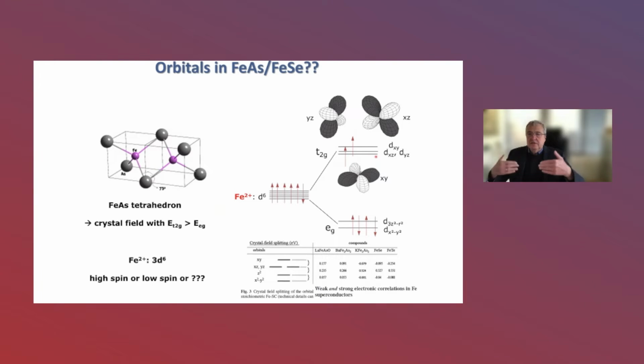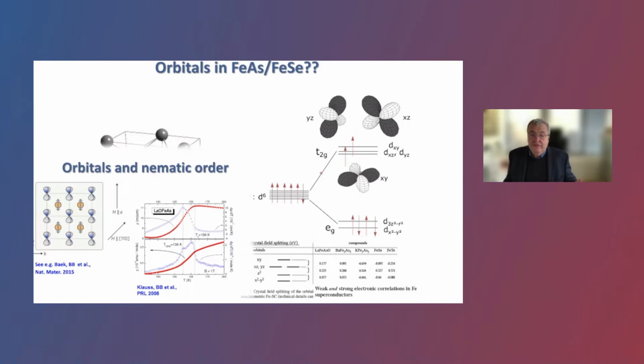In a metallic system, it's our bands which are degenerate, but this of course is the source of a strong coupling to the lattice. And this is also well known. We have this phase transition, which you already saw in the resistivity before. We have a structural phase transition from tetragonal to orthorhombic, which lifts this degeneracy. And it's already argued a lot that these orbital degrees of freedom play a crucial role when discussing this so-called nematic instability in these iron-based superconductors.